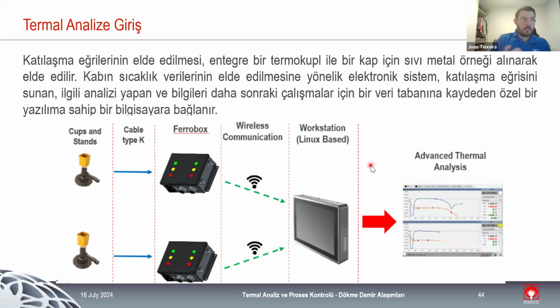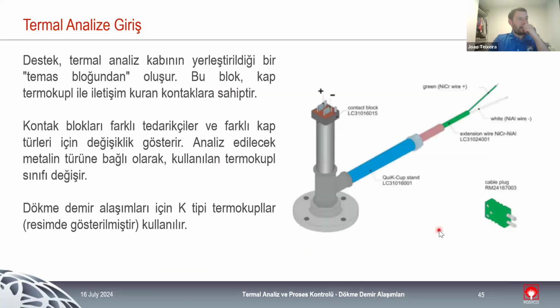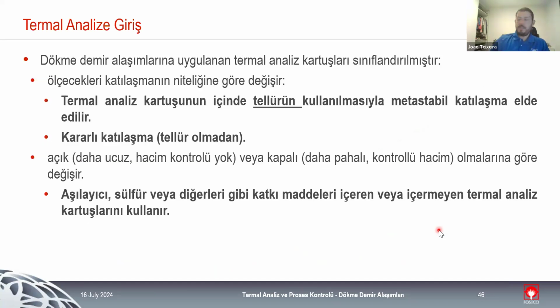For the particular case of Foseco, we use a Ferrolab 5, and it's a system that you see here. And the Ferrolab 5 consists of a cup and stand. The cup is where we pour the metal sample for the analysis. The Ferrobox, where we do the conversion of the thermic signal with the type K thermocouple to an electric signal for us to have a curve. And the workstation, where we can see the curve. And the stand is basically a place where we put the thermal analysis cup that connects the thermocouple to the whole system to convert the temperature into an electrical signal.